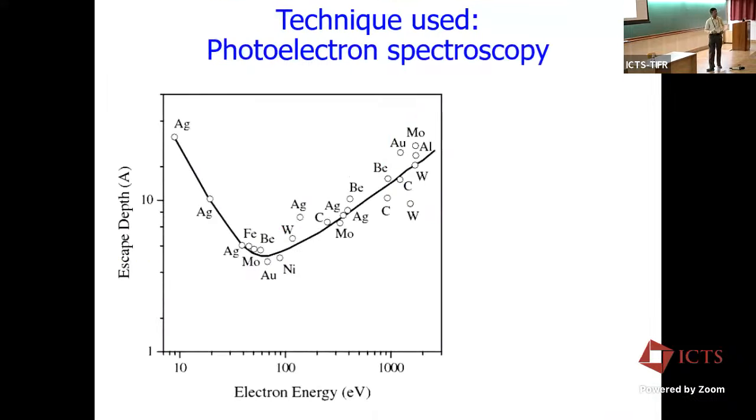How do you make it serve the layer-resolved sensitivity, the microscopic aspect? That comes from another interesting aspect. The photoelectrons are going to be generated at various depths, depending on where the photon gets absorbed by an electron and that electron gets knocked out. So the electron makes a transition wherever the photon is absorbed in the depth of the material.